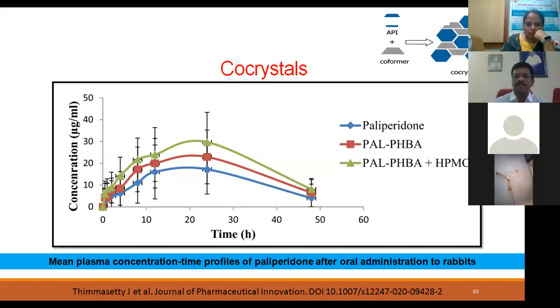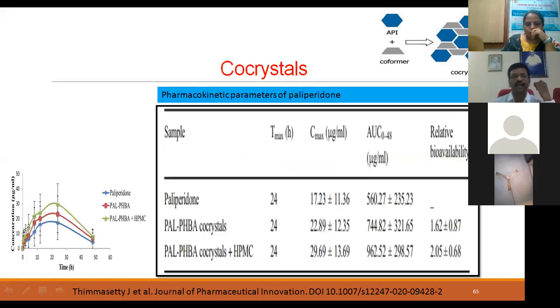We have taken several co-formers, prepared several co-crystals and subjected them to in vitro studies. From the in vitro studies, we understood that the co-crystals prepared from PHBA, para-hydroxybenzoic acid, showed very good results. Then we subjected paliperidone crystals alone, paliperidone co-crystals formed from PHBA, and paliperidone co-crystals prepared in the presence of HPMC, all three, to bioavailability studies. The trends are in this manner and the values are shown in the table. See, there is a rise in the Cmax from 17 to 22 with co-crystals, and from 22 to 29 with HPMC.